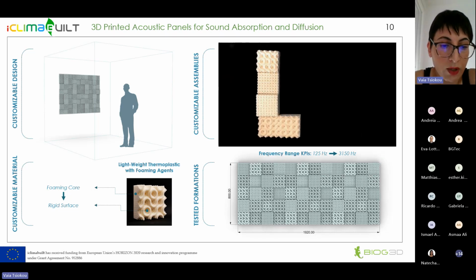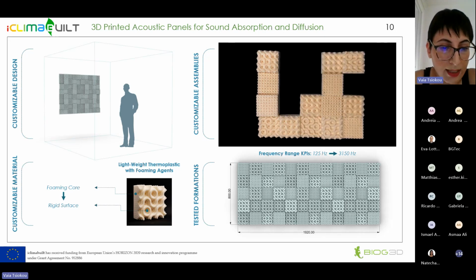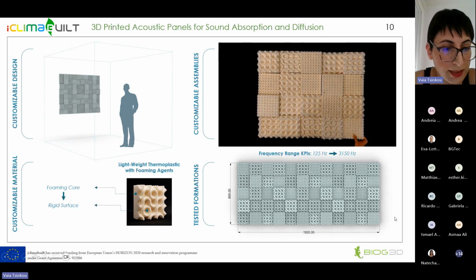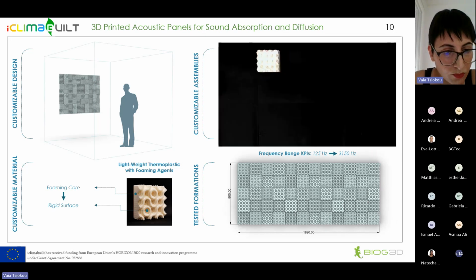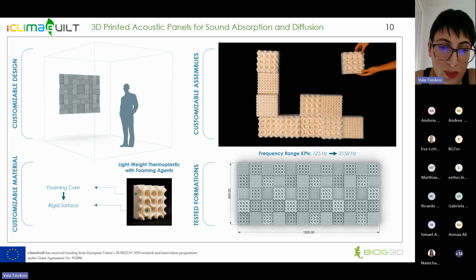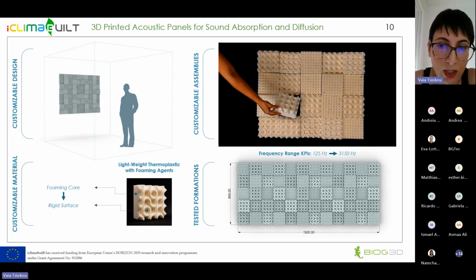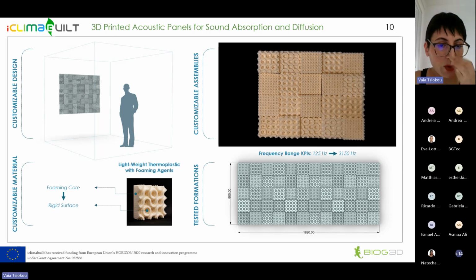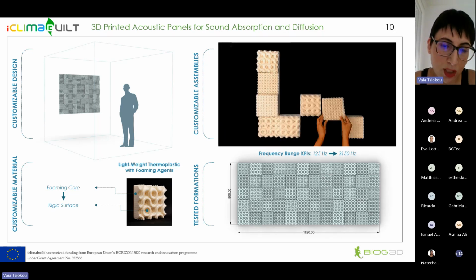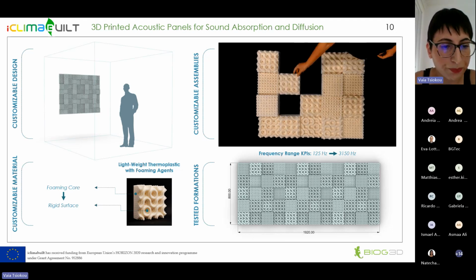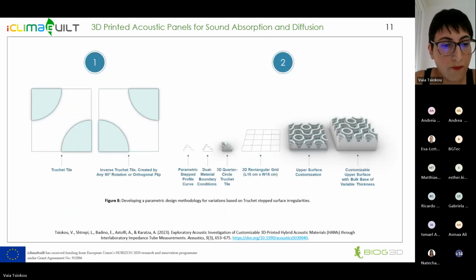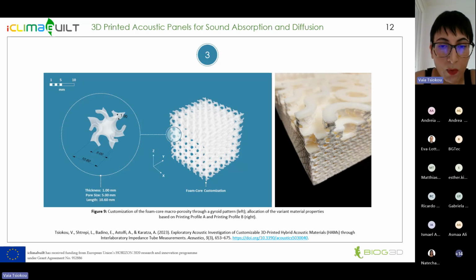This has been targeted through the implementation of a series of design typologies aiming for different frequencies within the human spectrum, as well as through customizable material properties, due to the thermoplastic material with foaming agents that activate at a certain temperature. For the diffusing properties, a parametric design methodology has been developed for variations based on true step surface irregularities. While for the foam core, the macro porosity has been customized through a gyroid pattern.